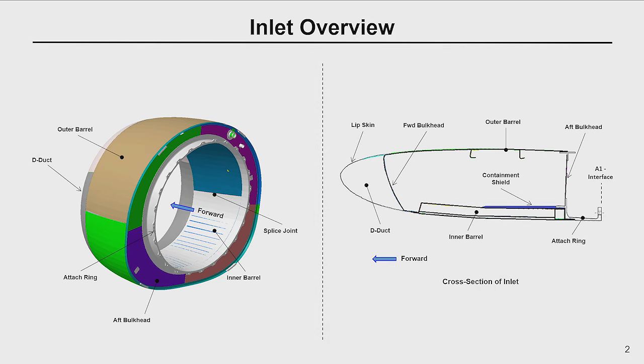And then we've taken some material samples from the penetrations in the outer barrel. The outer barrel is made out of aluminum. And through the material samples that we've taken in that location through the penetrations, we found traces of titanium. So that would likely indicate blade fragment debris or damage. However, as we said, the investigation is still ongoing, and we don't have full party consensus on that at this point in time.